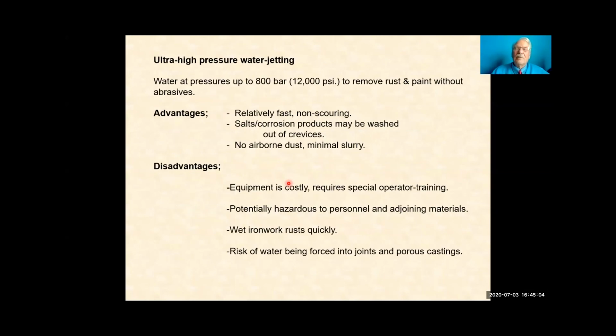Okay, why not do away with the abrasive altogether and have high pressure water, up to 800 bar, 12,000 pounds per square inch. You don't need abrasive at all then. It's quite fast, it's fairly non-scouring, so you can't do too much damage to the historic metals. You can usually wash the corrosion products off the surface. You may be washing some of them into porosity, of course, and into joints. And you don't have very much slurry because you don't have very much water. It's going out so fast, you don't need much of it. The disadvantage is that it's very expensive equipment. It's a great big engine to drive this equipment. It's extremely dangerous to the operators. They have to have special training and special protection. The ironwork, of course, will re-rust quite quickly.